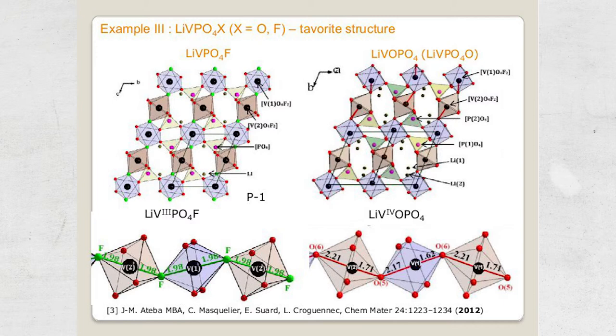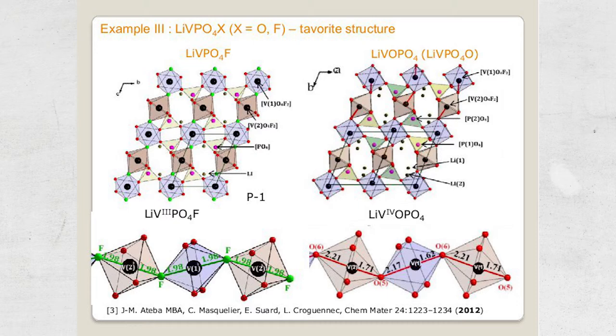The third and last example for the electronic structure concerns the LiVPO4 material. We can synthesize LiVPO4F or LiVPO4O — two materials with similar tavorite-like structures. The most striking structural difference is locally in the vanadium octahedra: in LiVPO4F the vanadium octahedra distances are quite symmetric, but in LiVPO4O we have alternating very short and very long V–O distances.